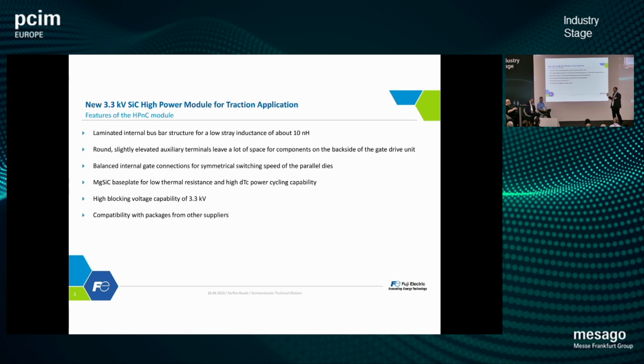Our module features a magnesium silicon carbide baseplate, and most traction modules have an aluminum silicon carbide baseplate. The magnesium silicon carbide baseplate has a lower thermal resistance, but it allows the same delta TC power cycling capability. Then we have a high blocking voltage of 3.3 kV, and of course package compatibility with other suppliers, which is always mandatory.